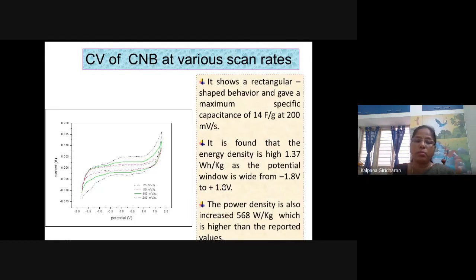From minus 1.8 to plus 1.8. And the power density is also increased, around 568 watt per kg, which is higher than the reported value.